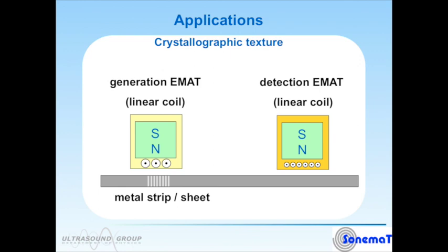So how we do it here is we have a generation coil on one EMAT and a detection coil on another, and we carefully select a particular kind of wave, a guided wave, to go from the generation to the detection EMAT. Because it's non-contact, we don't significantly affect the system that we're measuring, and we're able to make very accurate velocity measurements.